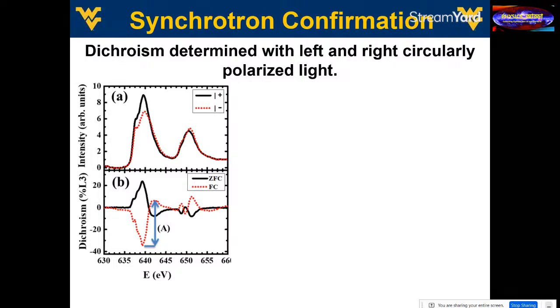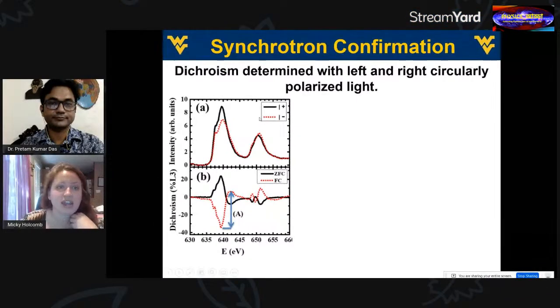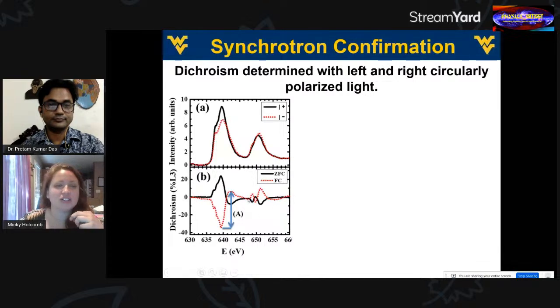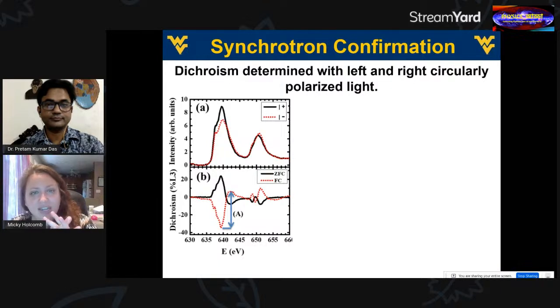So I told you a little bit about X-ray absorption already, and how you can get differences depending on which direction the magnetization is in the system. This one's a little more dramatic than my last example. And you could subtract these two. And you don't even need to know much about it to see that the black and red ones here on the bottom are the subtraction of the curves on the top. And we can get it to flip, to reverse, depending on whether we did zero field cooling or field cooling in the measurements. So this is a technique where we did not even have to apply a magnetic field, and we were able to get this.